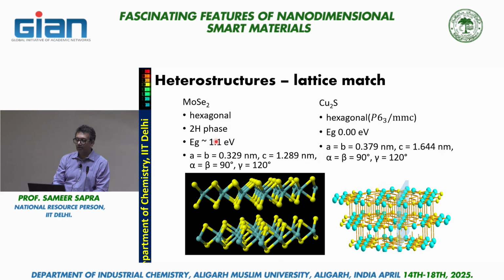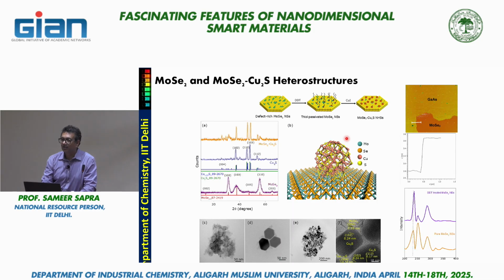The other thing is, look, cuprous sulfide happens to be, if it's actually cuprous sulfide, a zero band gap material. So maybe I can also get some interesting properties. Well, of course, he didn't form cuprous sulfide. What he formed was copper 1.97 sulfur. So it has some vacancies and it's a different kind of material. But what you have over here is you take these defect-rich molybdenum selenides, and since it has defects, it's hungry to quench those defects.